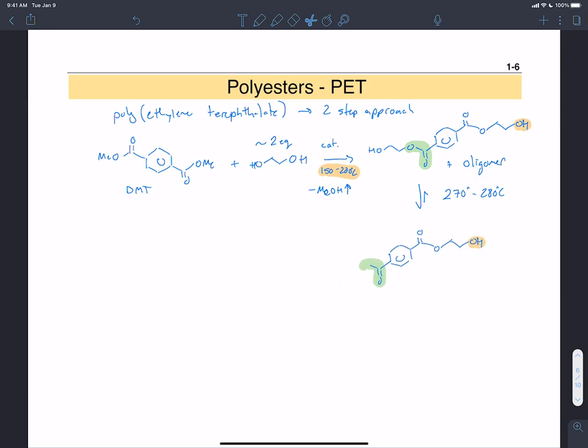And this involves the same sort of idea because we're going to end up being in equilibrium between some sort of polymer or oligomer that has been generated. And also, we'll start making ethylene glycol as a byproduct in the equilibrium. But now that we're at even higher temperatures, this is well above the boiling point of ethylene glycol. So when you apply vacuum, now this can just be distilled off and removed. And this will end up pushing the equilibrium all the way forward to actually make high molecular weight PET,